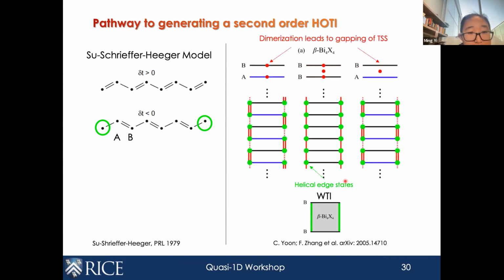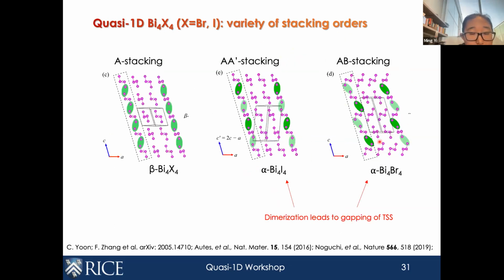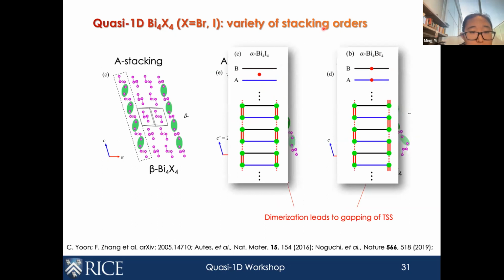But if we introduce dimerization, there are two ways to dimerize this. We can have a situation where the inversion center is in between the layers, in which case the dimerization on the left-hand side and the right-hand side are exactly the same. Or we can have the inversion centers within the planes. In that case, there's an offset between the dimerization on the left-hand side and the right-hand side. And there's a distinction between these two types of dimerization. These two types of dimerization can be realized in the AA prime stacking and the AB stacking. More specifically, in the alpha phase of bismuth iodide, this would be consistent with this kind of dimerization, while the alpha phase of bismuth bromide is consistent with this kind of dimerization.